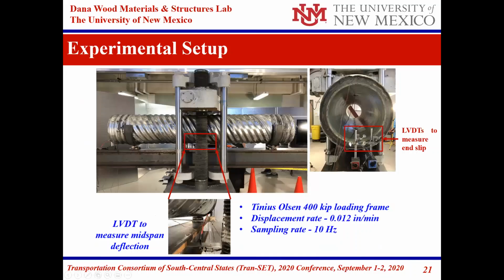This is a 400 kip actuator where we can actually have a displacement control test. At the bottom here, you see this is a support. It is a very large steel beam that would allow, at a 400 kip load, less than 0.01 millimeter of deformation. So it's a stiff beam, not moving. We created the supports, as you can see, circular supports here, one as a roller and one as a hinge, to actually allow the loading of the pipe as simply supported. You can see we have used LVDTs at the end to measure the end slip, and we also have LVDTs at the middle to measure the displacement.